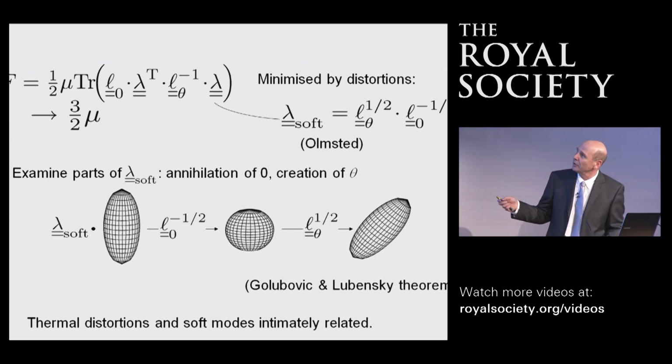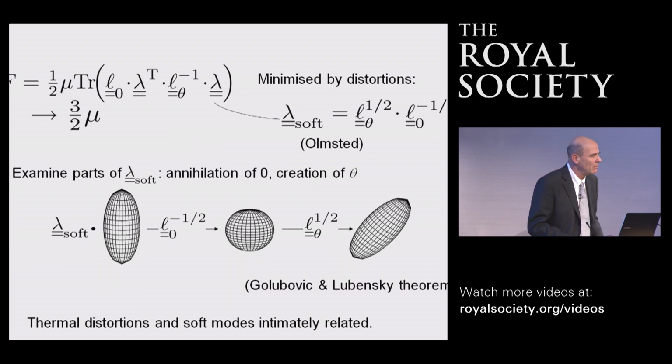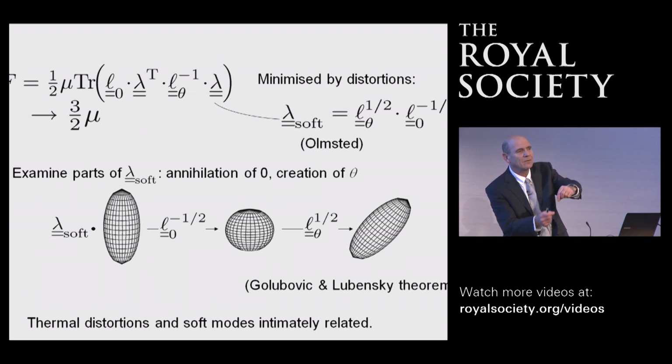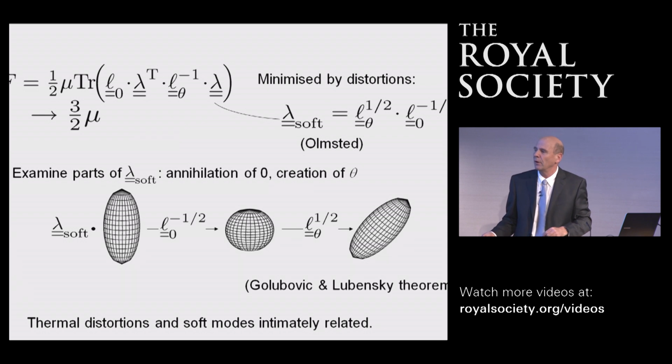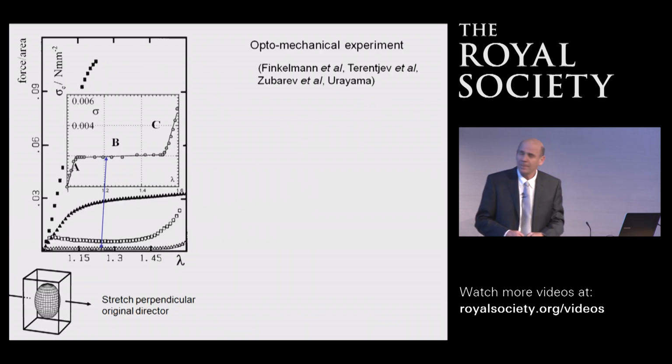And this annihilation by this guy of the memory of these tensors actually destroys the elongation this way, makes a sphere, rotates the sphere, elongates it that way. And there's a theorem to this effect that you can always do that in these sort of mobile systems. But the underlying message is, something that is capable of stretching up and down and is a liquid is then capable via rotations of giving you this soft elasticity. They're intimately related aspects of the same phenomenon.